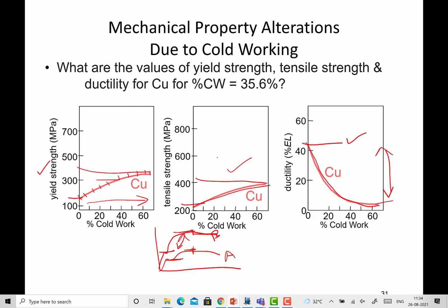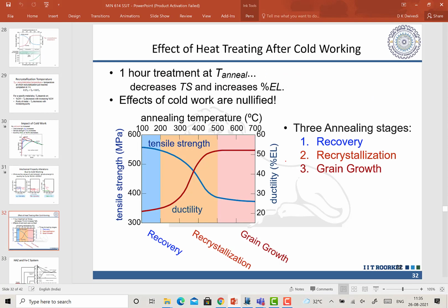So for steels it is huge, likewise for copper, but for aluminium it is limited, and this work hardening capability is usually linked with the stacking fault energy of a particular metal. Lower the stacking fault energy, higher will be the work hardening tendency of the metal. So high work hardening tendency metals like cobalt, austenitic stainless steel, super alloys, they create a lot of problems during machining because of this hardening tendency. Cold worked metals will be experiencing the effect of heat more badly as compared to the other metals. So this is an important thing.